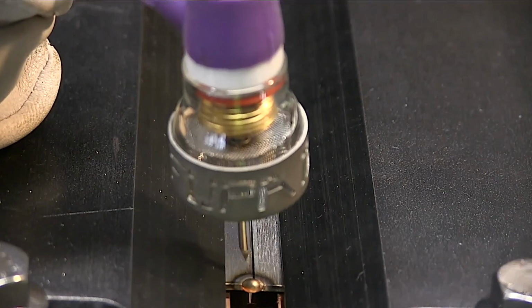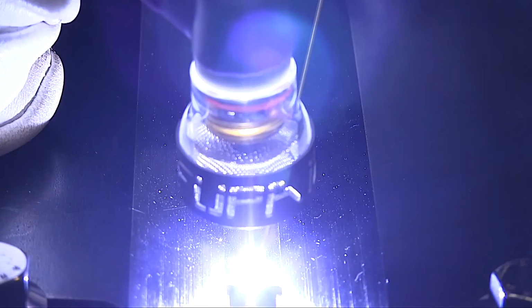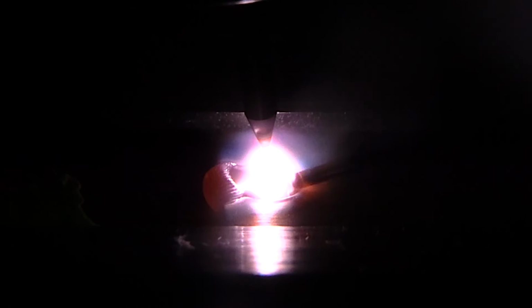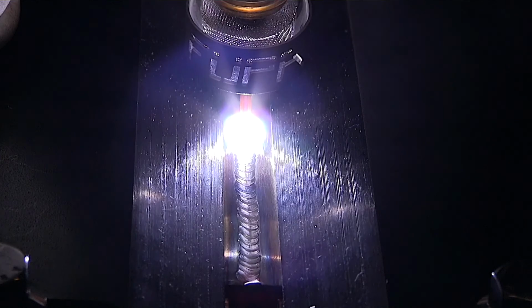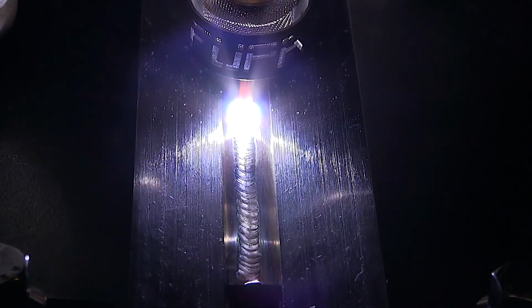Now, something I didn't mention, there's a reason why I'm welding this in halves, and it's called backstep welding when I weld to a previous weld. And that basically is because this is what I required when I had to administer these tests. I thought it was a pretty bad idea not to have any stops and starts, so this at least demonstrates the ability to taper off and not leave a crater crack or a crater eye on some of these crack sensitive alloys. So you can see there in slow motion, it works just as well coming from a tack as it does tying into a tack.